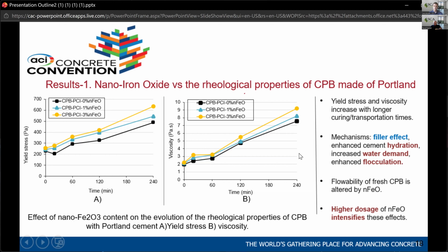It's because when there is more hydration, there is a layer of water. This is the effect. The layer of water would take over the machine's viscometer when it rotates. It's a disc which rotates. That's why it shows the viscosity more, but it's not actually so in practice.